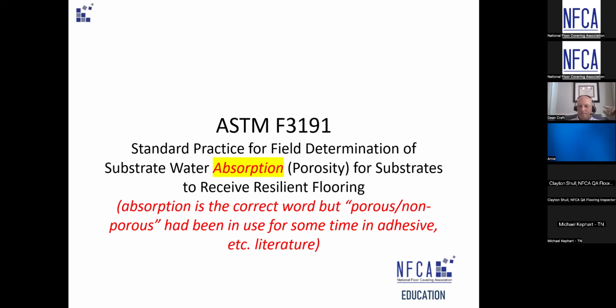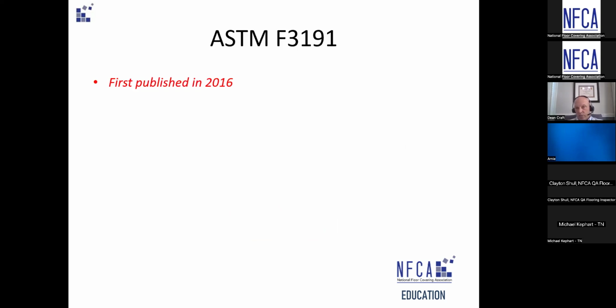Would you say a good absorption test is basically a bond pull test? Well, the absorption test is a separate test. This right here, the water drop test, is your absorption test. Yeah, well, the reason I say it is because you can do the droplet test on regular concrete, and maybe the timing is healthy for the time it takes that droplet to disappear. But then you come along with an adhesive that doesn't react the same way, and it essentially turns the surface into a non-absorbent. At that point, a bond test is probably what is going to tell you that you've got healthy absorbency, or that you have the right product for the substrate conditions, not the droplet test.